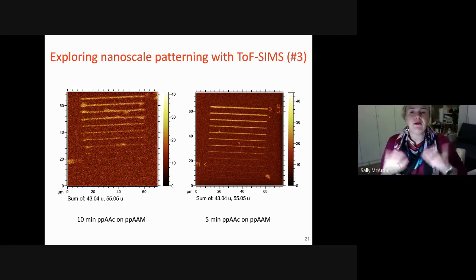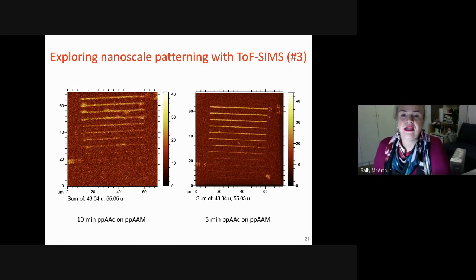So you can see a number of things in this image here. When the film's thicker, you can see we've struggled to delaminate it. The boundaries, you can see there's tearing associated with removal, and you can see that we're struggling to see the resolution at these smaller features. Whereas when we drop that second coating's film thickness down, we can start to imagine, if I squint really hard, that the 50 nanometer line is still there, but the 100 is absolutely there, the 200, the 300, the 400 as we move through. And so we can see the chemistry, and we can see that the pattern resolution is better under those conditions. And so we're absolutely able to get to submicron patterns in this way.